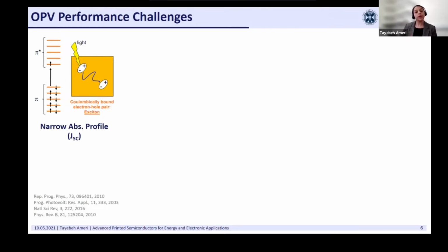And it means when you excite an electron from the HOMO level to the LUMO level, they are forming a tightly bound electron hole pair called exciton. And it's narrowing the absorption profile of our material compared to an ideal flat absorption like what silicon has. And it's reducing the short circuit current of the device, Jsc.